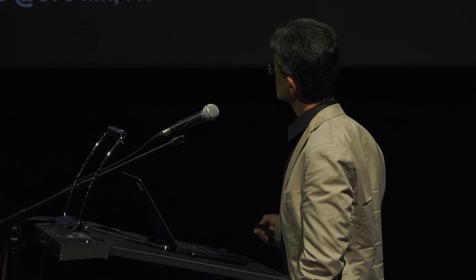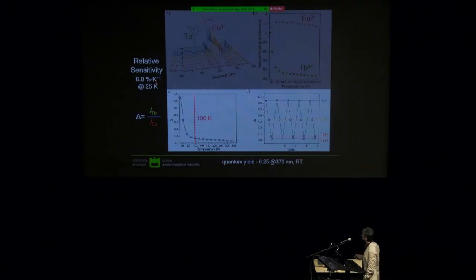And it has quite good relative sensitivity, about 6% per Kelvin at 25 K, so in the cryogenic range. So we developed a lot of these thermometers based on different metal frameworks, metal organic frameworks, and also one silicate or two.